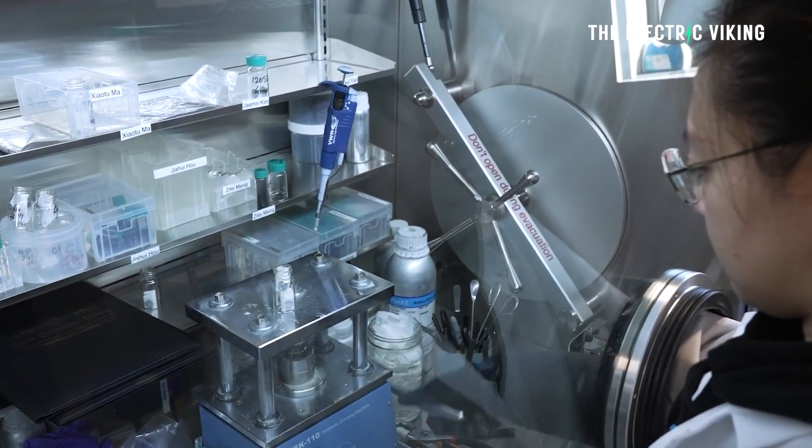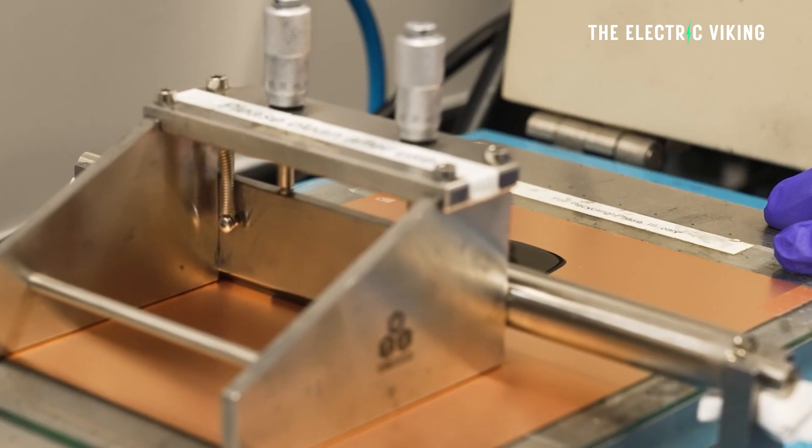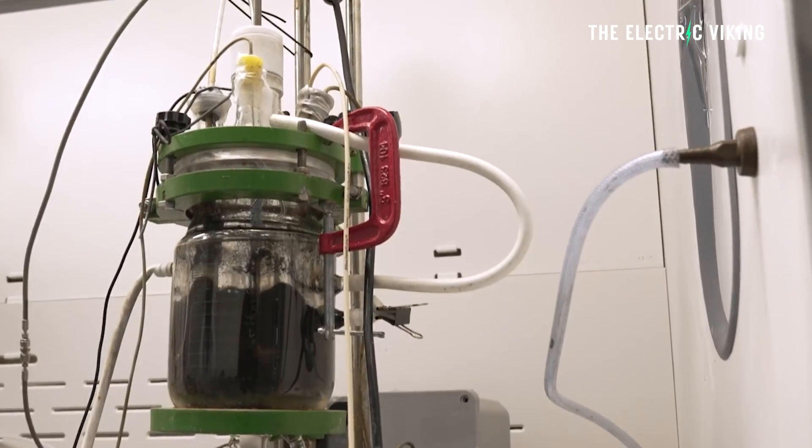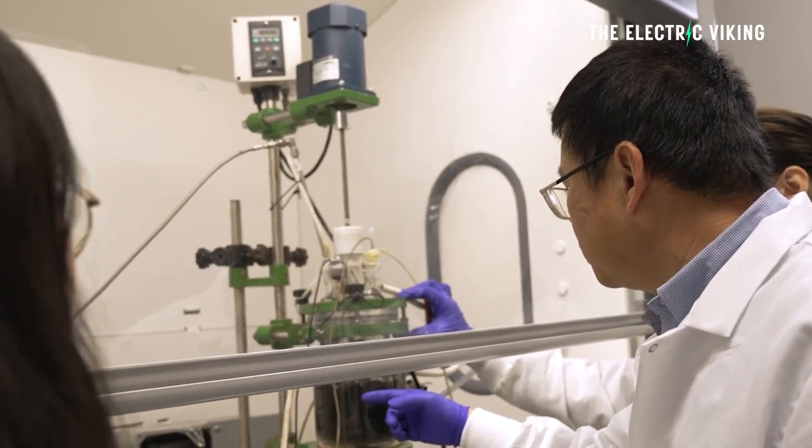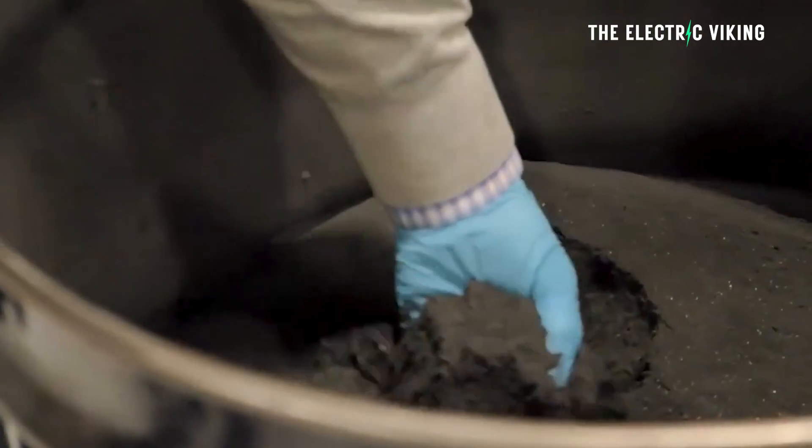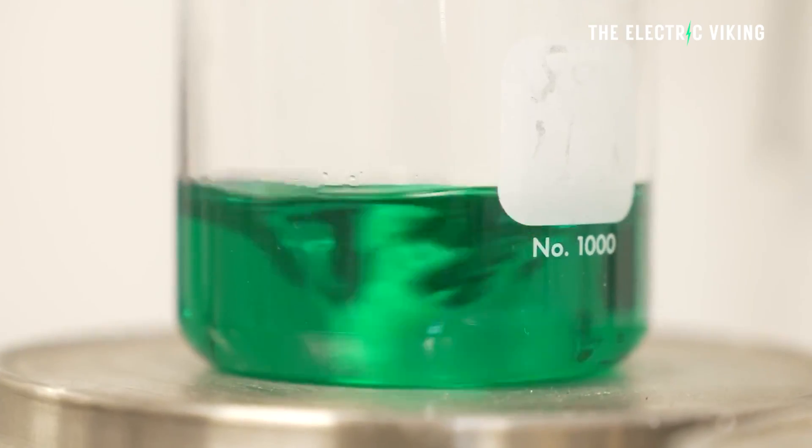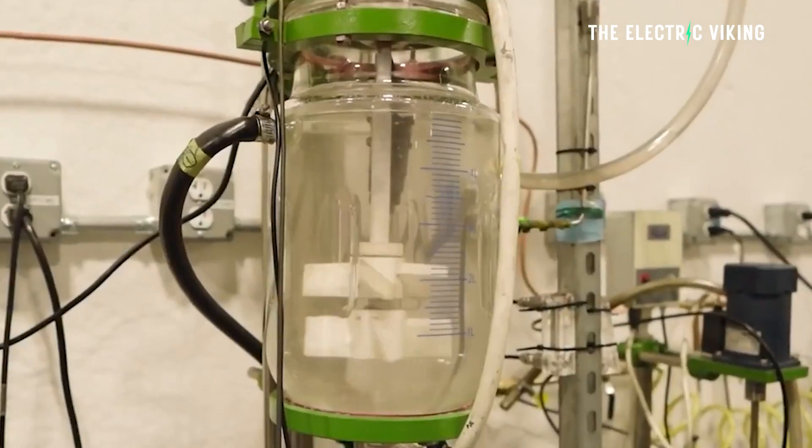The researcher's process, in contrast, is much like Tesla's, and it's involved with mixing together dry powders that were electrically charged, so they will adhere when sprayed onto a metal substrate. The dry-coated electrodes were then heated and compressed with rollers.